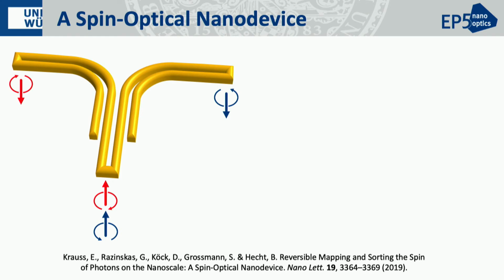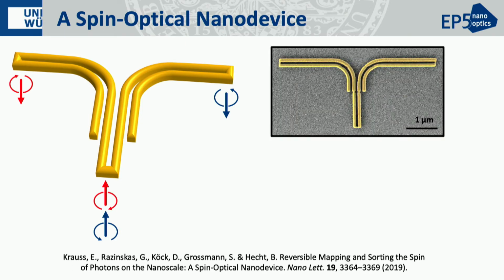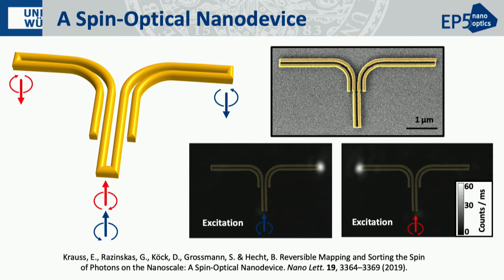So with the gold platelets as a very exact material at hand, I was able to directly and very accurately reproduce the geometrical dimensions obtained by numerical simulations, and was then able in optical measurements to confirm that the device is working. So you can basically see here an excitation with one or the other helicity, and you can see that the signal switches from one side of the device to the other.